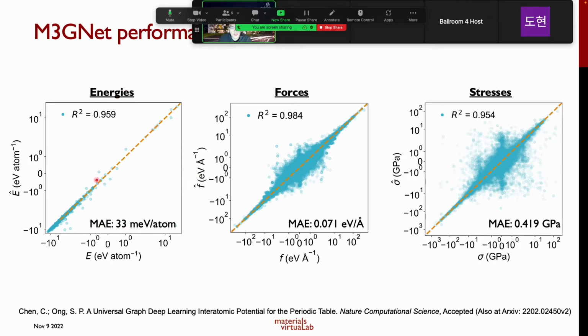We can actually achieve energy error of within 33 meV per atom. So this is extremely good. Just to reiterate, these are for the entire periodic table, and it works universally across all structures and all chemistries. The force errors are also very reasonable, 0.07 eV per angstrom, and the stress performance is not so great, but that's mainly because the training data does not have very well converged stresses to begin with.